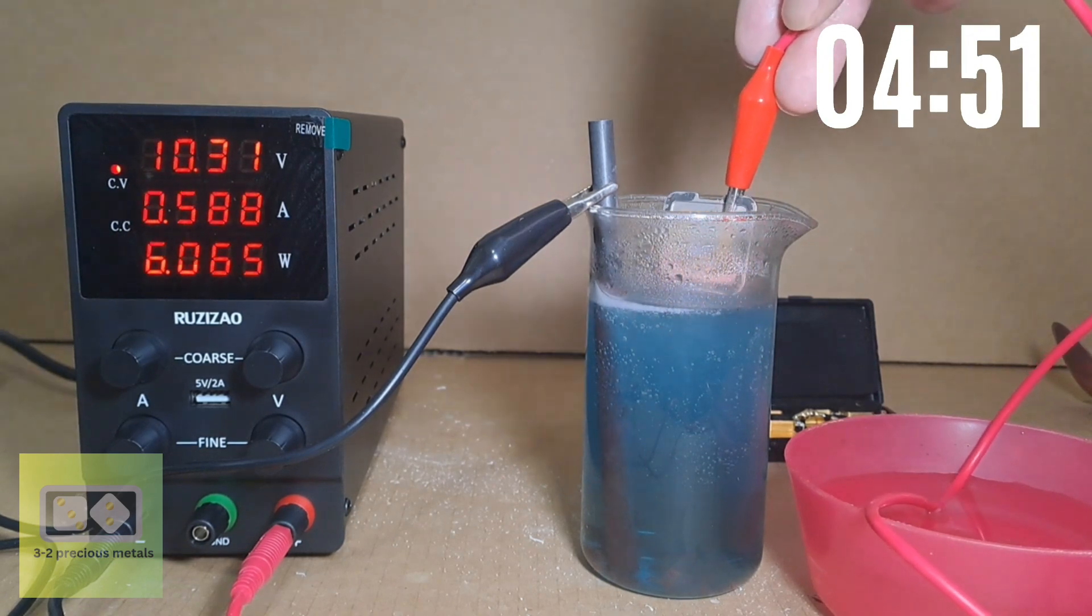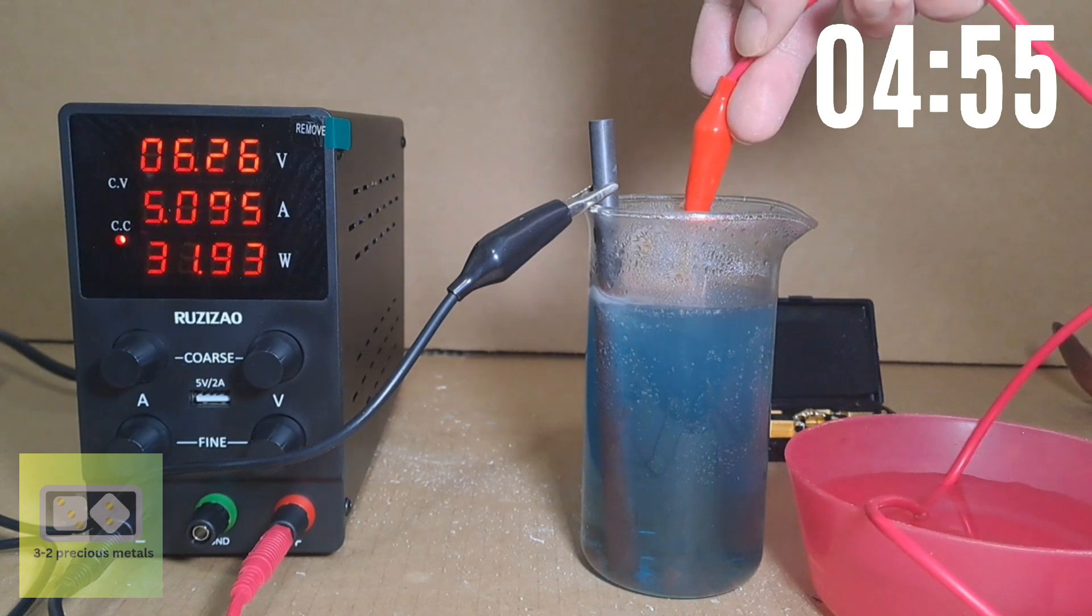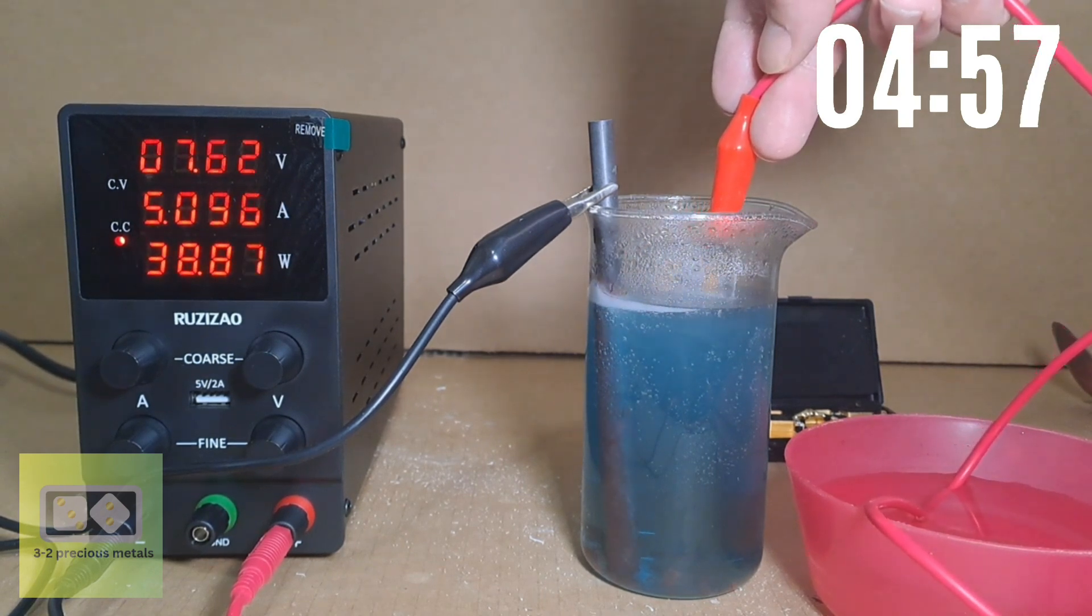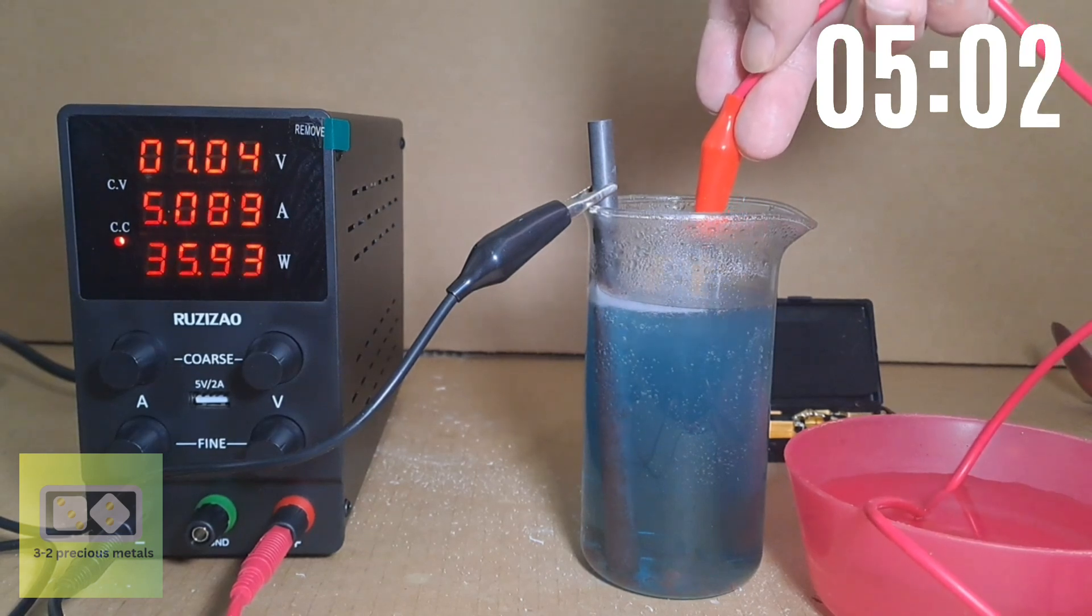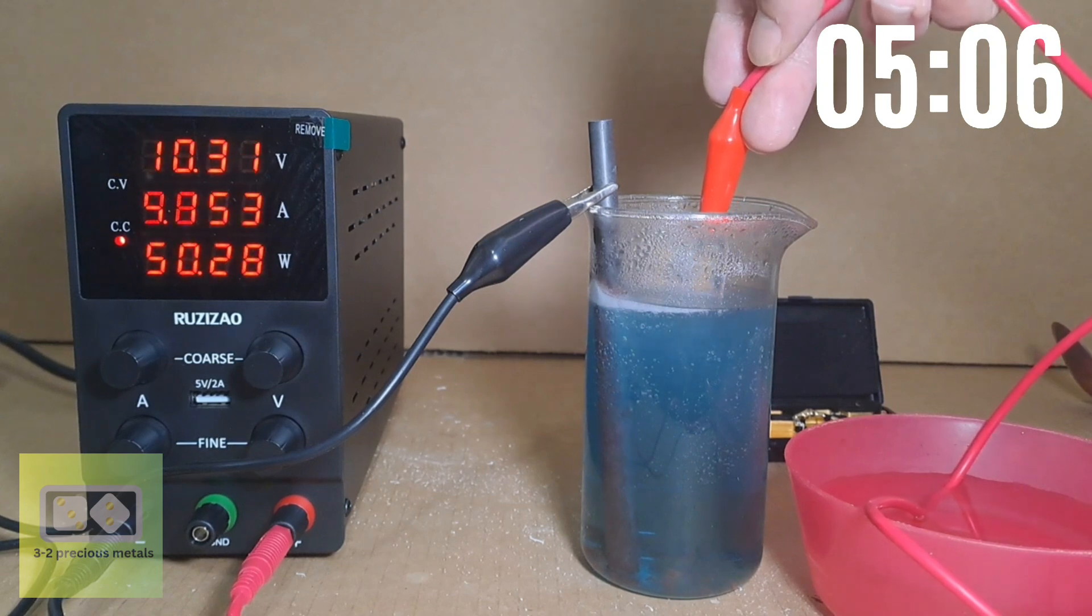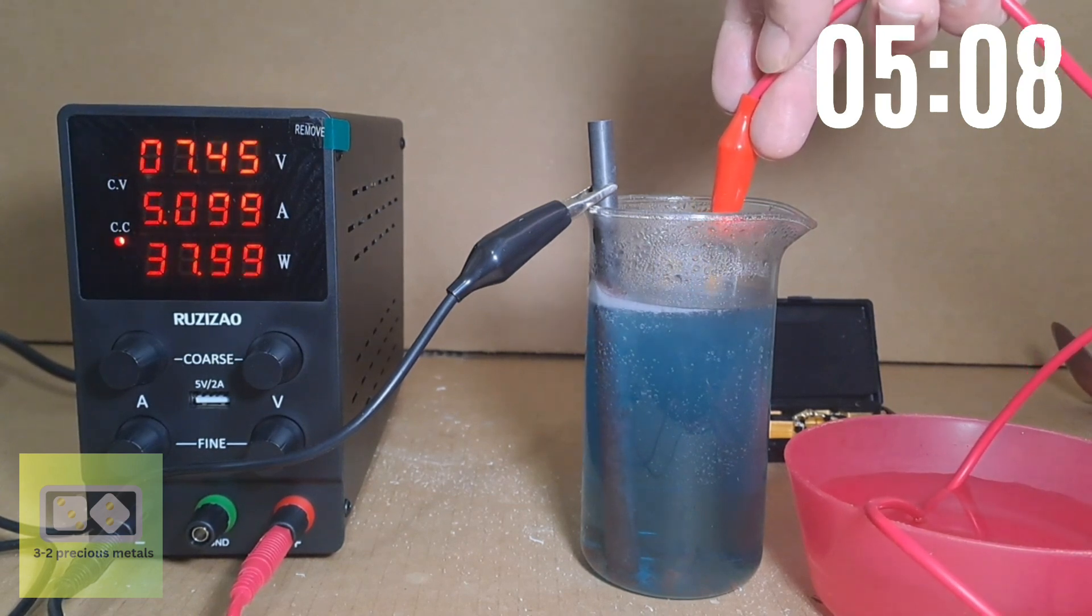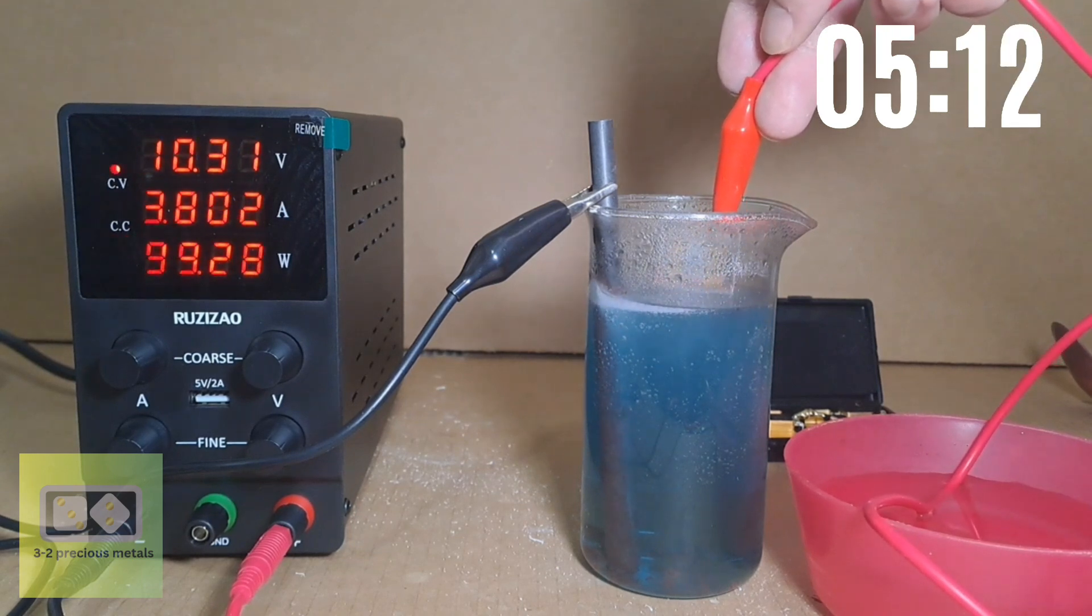So, what can we conclude from this? Well, it looks as if the dilute acid is causing the copper underneath the gold plating to be oxidized. This is allowing the copper to go into the solution, which is then deposited at the cathode. It's eating away at the copper behind the gold, which is coming away in little tiny flakes and mixing with the reduced copper.